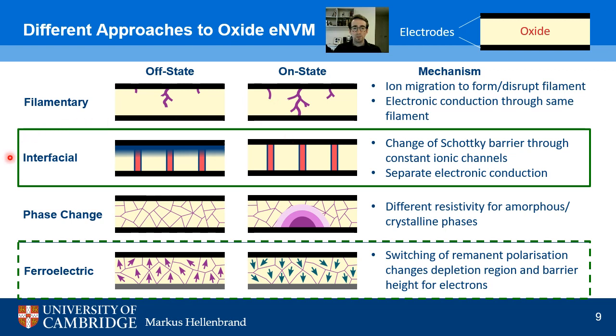For that reason, we are following this interfacial approach, where we have predefined paths of oxygen vacancies, so they will not move inside the second of the materials, but just inside the pillars that we make inside this matrix of the other material. And our hope is that by this we can reduce the variability and randomness in this other approach.